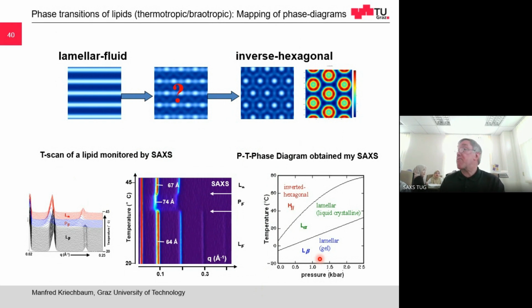Okay, we can also do time-resolved measurements in the laboratory. In that case, we make a slow heating scan. And we want to investigate what happens if we have a phase transition from the lamellar fluid into an inverse hexagonal nanostructure. So in that case, we do maybe 1 minute exposures over several hours, and we heat our sample up. And this is such a time-resolved temperature scan where we go through different phases.